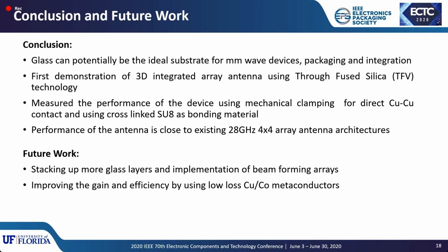And this is the first demonstration of a 3D integrated array antenna using through fused silica technology. We measured the performance of the devices using mechanical clamping for direct copper to copper contact, and we also used cross-linked SU8 as a bonding material. It is also important to note that the performance of this antenna matches closely with the existing array antenna architectures, and also the footprint of this structure is minimum compared to the other devices.